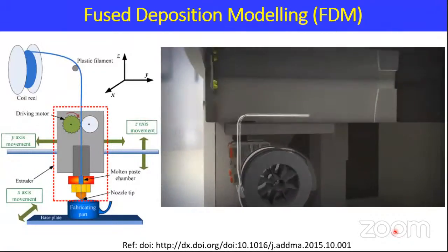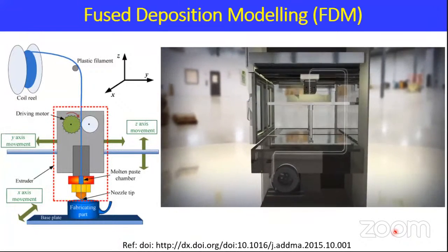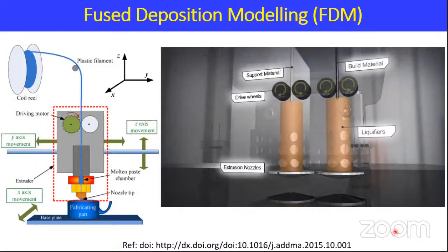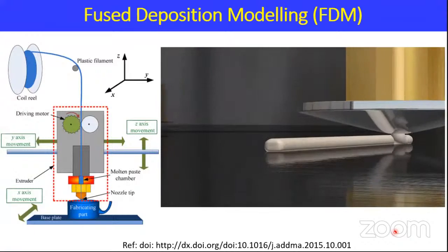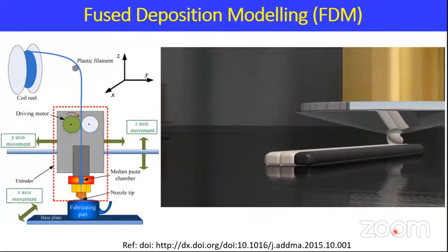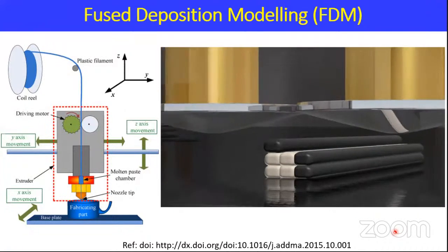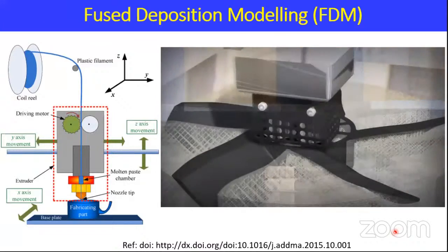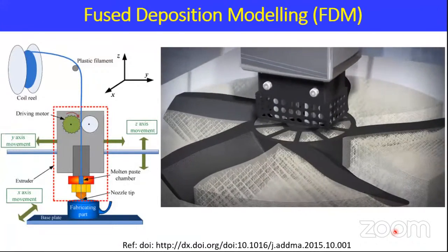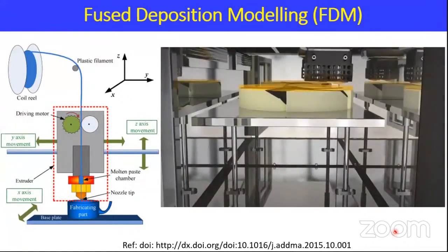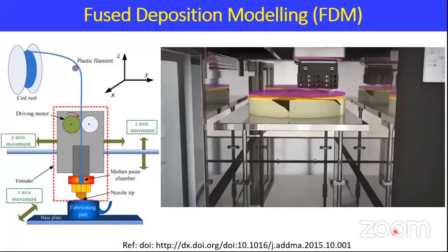Thin thread-like spools of thermoplastic and support material are used to create each cross-section of the part. Similar to a hot melt glue gun, uncoiled material is slowly extruded through dual heated nozzles. The extrusion nozzles precisely lay down both support and thermoplastic material upon the preceding layers. The extrusion nozzle continues to move in a horizontal XY plane while the build platform moves down, building the part layer by layer.